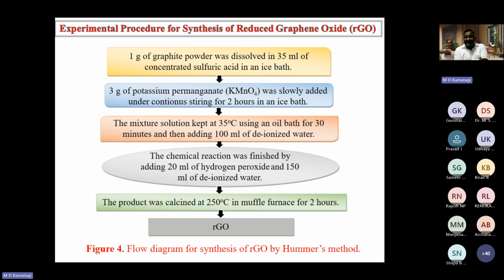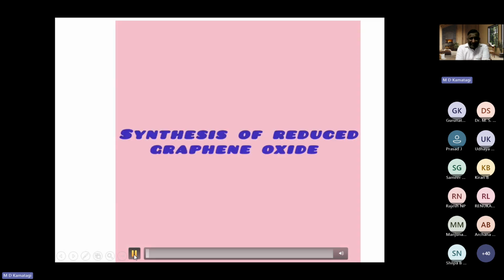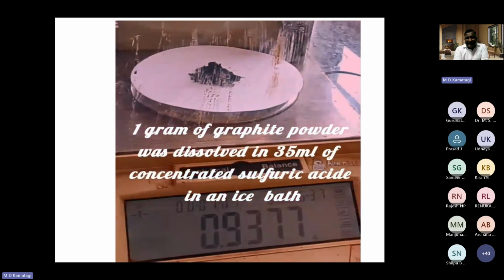In the meantime, the chemical reaction was finished by adding 20 ml of hydrogen peroxide to reduce it from graphene oxide to reduced graphene oxide. The product was calcined at 250 degrees Celsius, and then finally we obtained the reduced graphene oxide. We'll show a video wherein we have synthesized reduced graphene oxide.